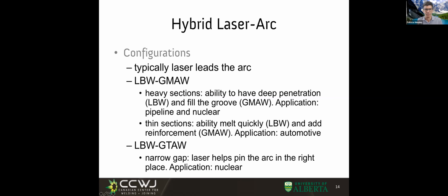Where is this used? Heavy sections, like, for example, pipeline, or for example, nuclear. People have been trying to do this in pipeline. I have seen it, but here's one of the problems. The steel for pipeline is designed to be rolled and thermomechanically processed, and that will give you a good pipeline. If you melt it, when it goes solid, it is nothing as good as the original material. It's typically very hard and brittle, especially for the very fast cooling rates of the arc.